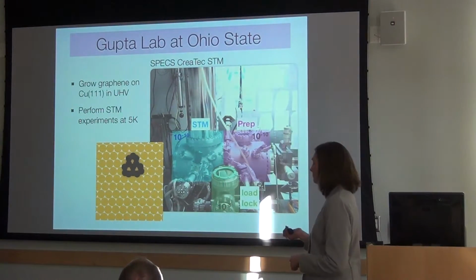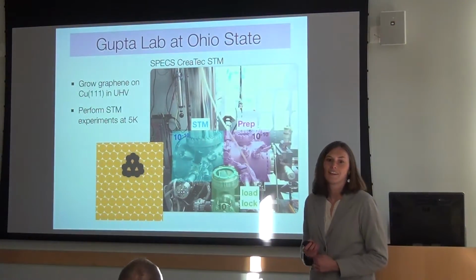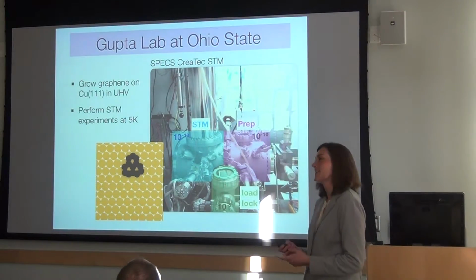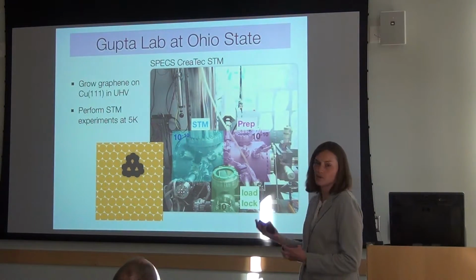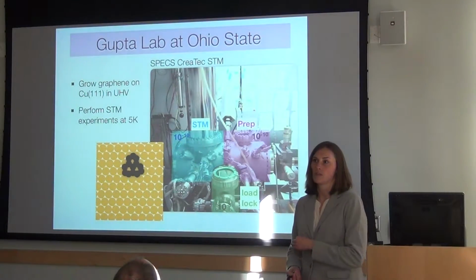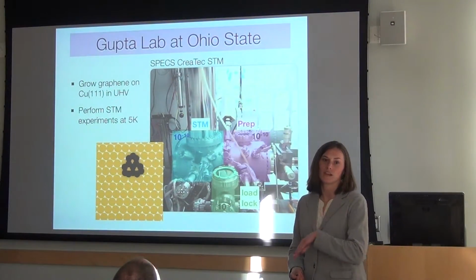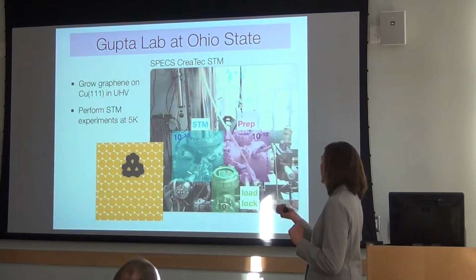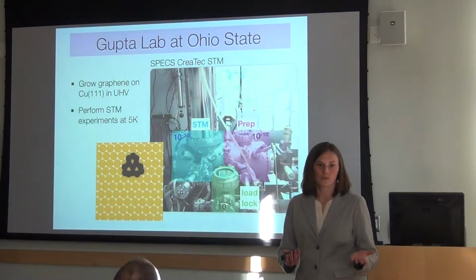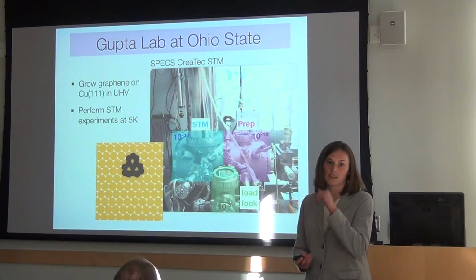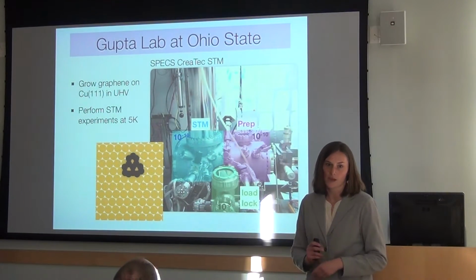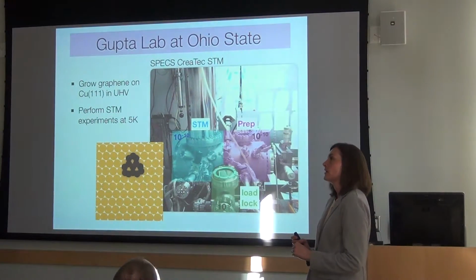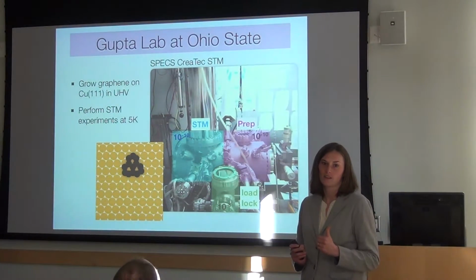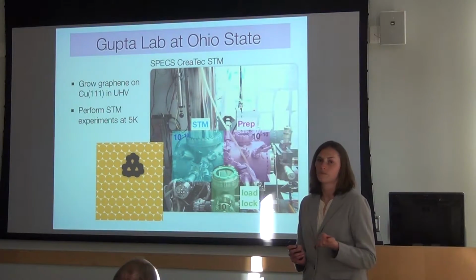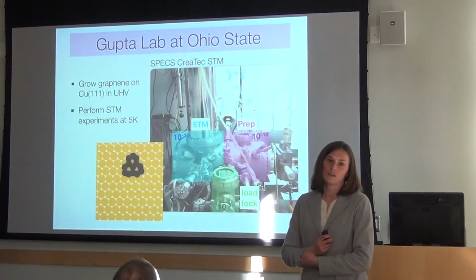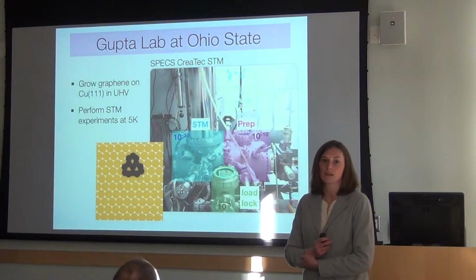What's getting them dirty inside an ultra-high vacuum chamber? It's kind of amazing, isn't it? One thing is that you're heating this surface up and cooling it down. You have to cool it down before you transfer it into the cold chamber to conserve liquid helium. And as it's cooling, anything that hits it is going to stick there. So you want that cooling process to happen really quickly. There's a rule of thumb that you're going to have some number of particles hitting per minute, I think 1,000 particles per minute at 10 to the minus 6.